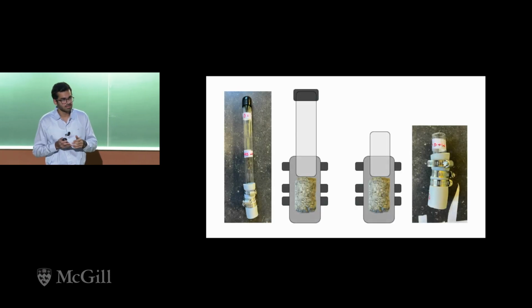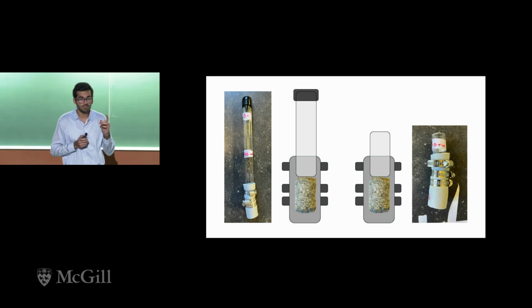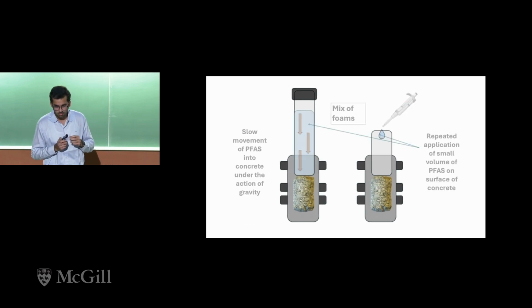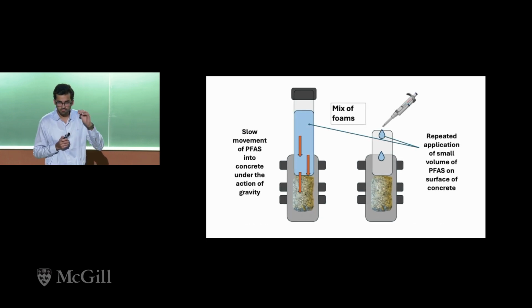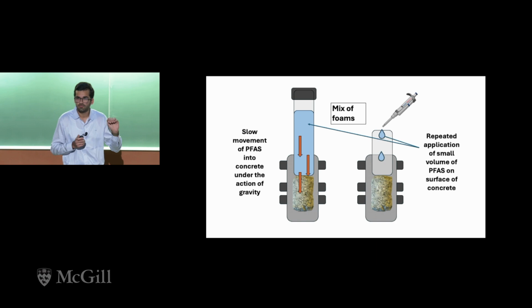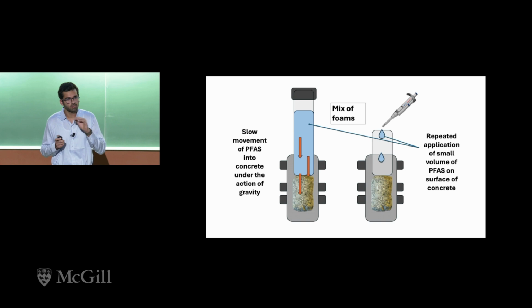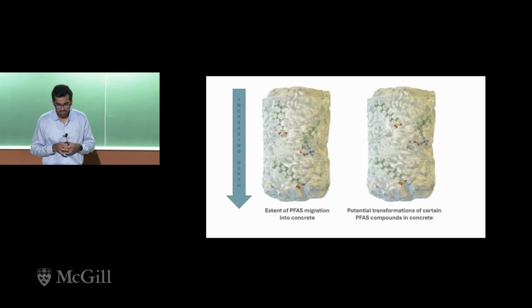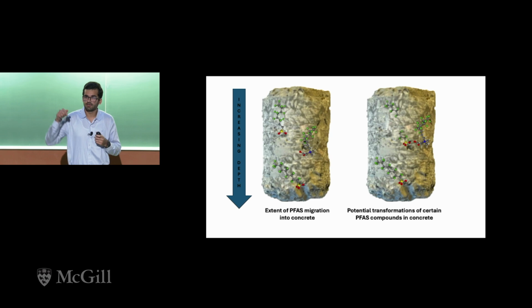Through my experiments, I'm trying to intentionally contaminate the concrete cores in lab with a mixture of not 1, but 3 different firefighting foams. And this exposure will be through 2 different methods. The first one will be a slow movement of these compounds under the action of gravity. And the second one, I'm repeatedly applying a smaller volume on the surface of concrete. I will take regular samples, and at the end, I will drill into the concrete to get the PFAS adsorbed